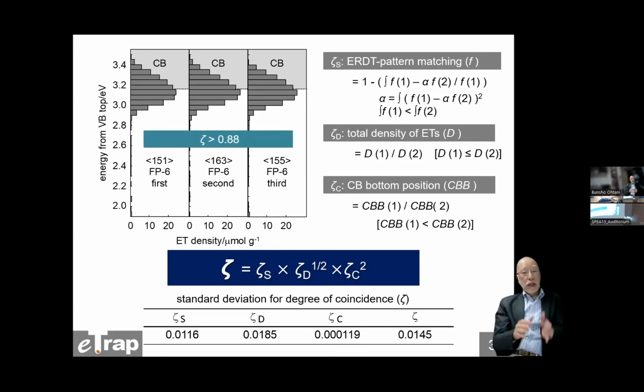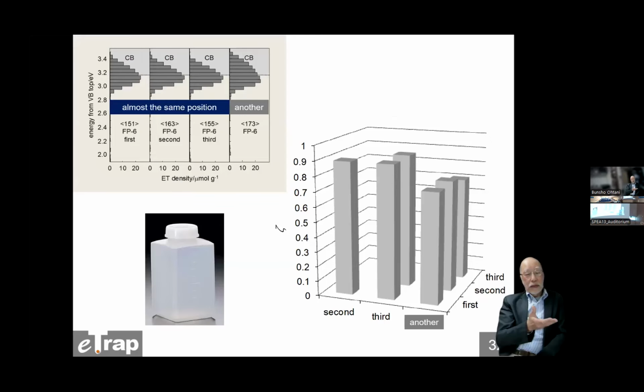And those 3 pairs of samples show a degree of coincidence almost higher than 0.9. The highest one is 0.95. And that means those samples are taken from almost the same position in the same bottle. So therefore, if the zeta value calculated by using this equation is higher than 0.9, we can say that those 2 samples are identical, the same. But if the sample is taken from a bit different position, the shape is clearly different, and the zeta value decreases to almost 0.7, from 0.9 to 0.7.